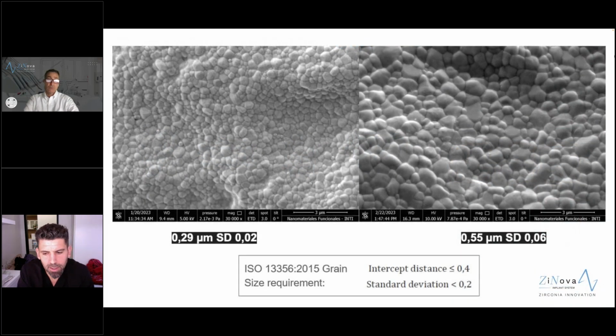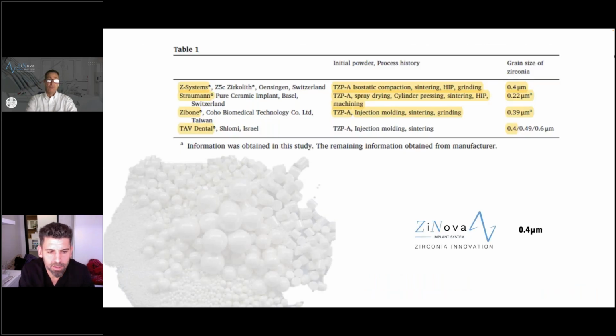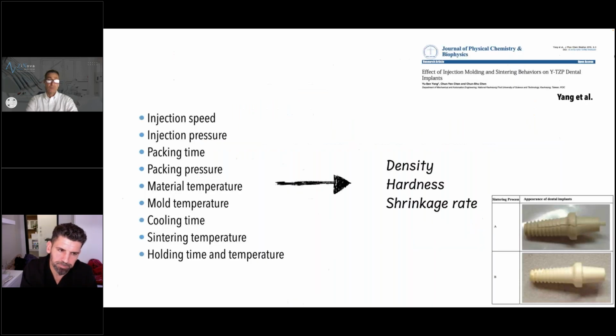The grain size, there are very specific ISO grain requirements. It should be 0.4 microns with about 0.2 micron standard deviation, and all of the companies have to follow this ISO standard. You can see here some of the companies, what the grain size of zirconia is. It's typically around 0.4 or so, as you can see. Our implant system, the ZiNova implant system, is at 0.4 microns. Everybody has their own secret sauce, let's say, but we all have to follow this ISO standard.